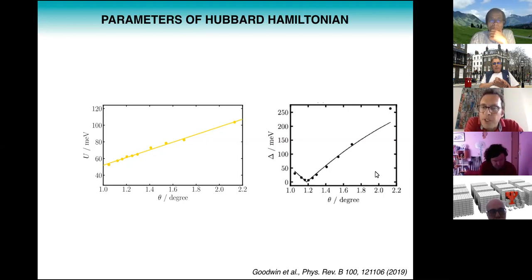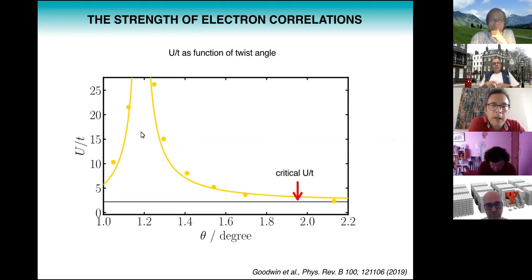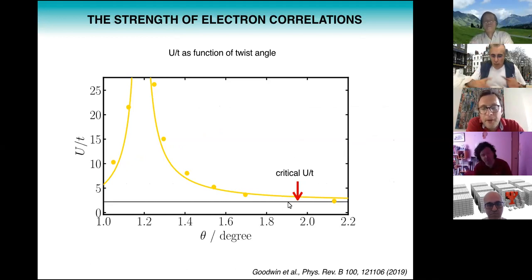But on the other hand, we know that the hopping is proportional to the bandwidth, and so here I'm showing you the bandwidth as a function of twist angle, and of course that goes to 0 at the magic angle. So we would expect, if we calculate U over T, that at the magic angle the thing blows up, and it does. But the question is, what does it mean?